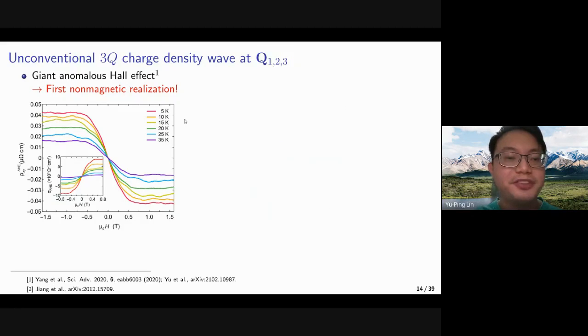So the first observation is that if we look at the charge order and do a magnetic field transport measurement, the material actually shows a giant anomalous Hall effect at this value if we apply the magnetic field. And it is similar for the A atom being potassium or calcium. It is interesting because it is the first material that realized the giant anomalous Hall effect which is not magnetic. The previous giant anomalous Hall effect measurements were done for ferromagnetic materials, and this is the first non-magnetic one.